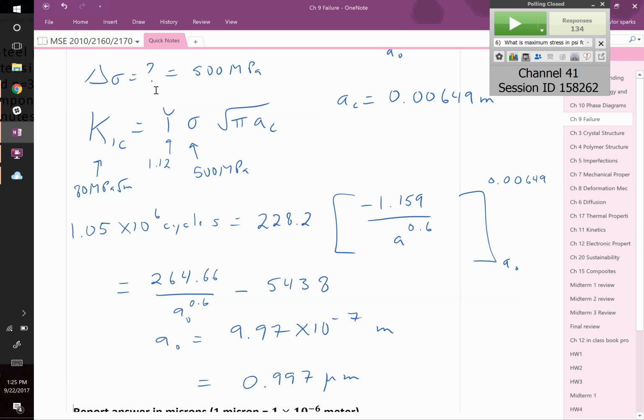But also, if there's a little bit of liquid at the tip of that crack, it can undergo stress corrosion cracking, and the crack can grow because the liquid dissolves the ceramic material at the tip of that crack. Again, normally you might not think that your dinner plate is soluble, but at the tip of a very high curvature, meaning very small radius of curvature crack, there's significant solubility which incrementally advances that crack length.